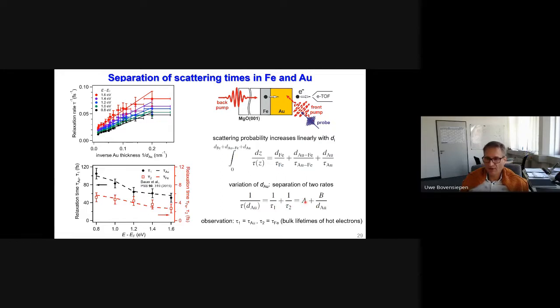So we now fit our data, which we plot here in this linearized representation with an offset and a slope, if you plot the data over the inverse gold layer thickness. This is what we do here. So you see here the inverse relaxation time, which is the relaxation rate, plotted on the inverse gold thickness for different energies. And you see this actually works pretty well. So with this linearized representation, we can fit all the energies, and the slope and the offset here now determine this tau 1 and tau 2. And this is what we plot here. So tau 1 is plotted on this left axis, and tau 2 is plotted here on the right axis.